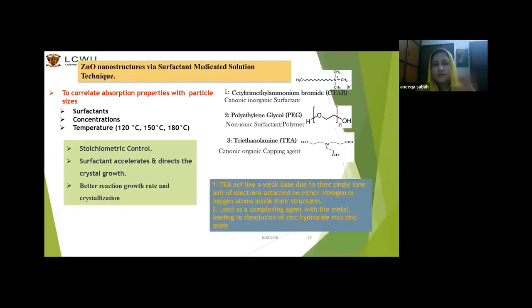These polymers react differently. TEA, triethanolamine, is a weak base due to the single lone pair of electrons attached on either nitrogen or oxygen atoms in their structure. They fit their position in the structure and are used as a complexing agent with the metal, leading to the dissolution of zinc hydroxide into zinc oxide.